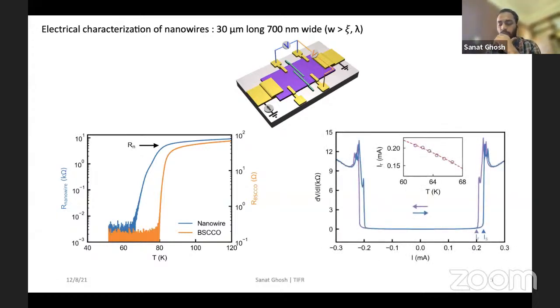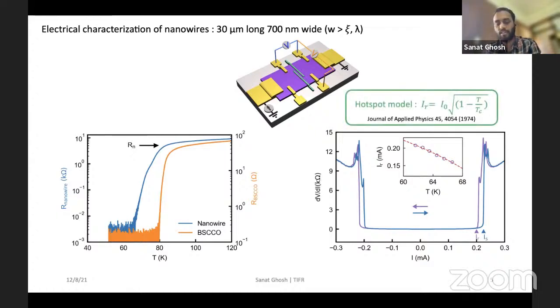Now we measured the bias dependent resistance. This is a differential resistance of the nanowire as a function of biasing current. And there are two things to note here. One is that there is hysteresis in the upsweep and downsweep of the current direction, and there are multiple peaks in the DVDI when it goes from superconducting to normal state. Now the hysteresis that we see can be understood by the hotspot model explained by Tinkham, where the consideration is that there is a normal spot on the nanowire, and that dissipates heat, and because of the heating effect you get hysteresis.